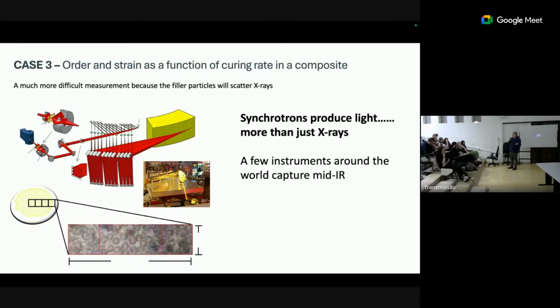And to do that, I can't do it with X-rays, because all those filler particles get in the way. They scatter the light in all different directions. But what I was very clear about at the beginning is that a synchrotron produces light across the spectrum. So it also produces visible light, and it also produces infrared. So now we have super infrared. It's actually not that much of an advantage over a lab source. It's about twice the flux, but it's slightly more structured. And so now what we're trying to do is see if we can detect the same things, strain and conversion, in a completely different way to anybody's done it in dentistry before.